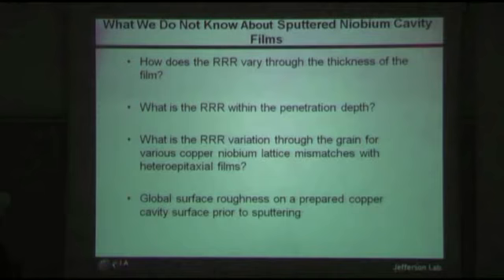The other interesting thing is, in the heteroepitaxial case, the niobium picks up the nearest lattice match of the underlying copper grain. This will start the film off with a lot of misfit dislocations that would vary from one grain to another. Also, you're depositing on each grain surface, which is a different crystal plane, as it continues its columnar growth to the penetration depth. None of those things we really know.